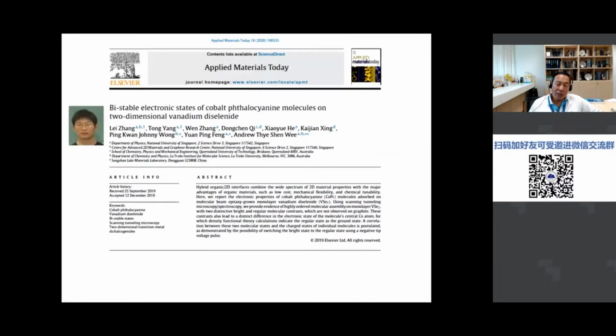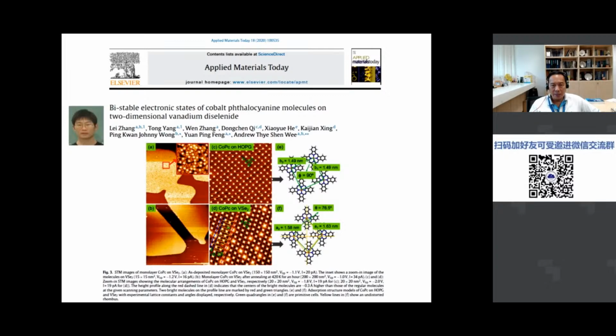So Zhang Lei in his PhD project was working on a related molecule, cobalt phthalocyanine, and he was working on cobalt phthalocyanine on vanadium diselenide, which we talked about earlier. So naturally, and of course in STM you can see the arrangements, and they self-assemble in this very nice periodic structure. So he did CoPc on HOPG, see this square lattice, and CoPc on vanadium diselenide, where it's a slightly distorted lattice over here. So the question we are asking now: can CoPc, just like cobalt, induce proximity magnetism in VSe2? Now, this work doesn't talk about magnetism, only talks about electronic effects.